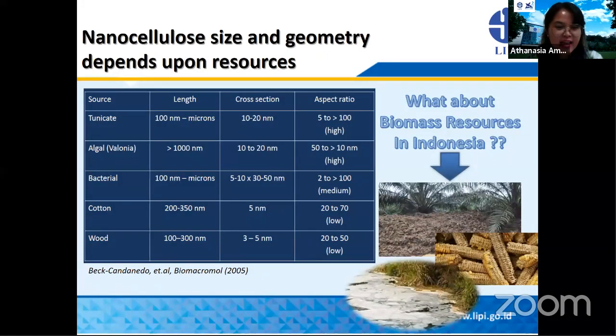Okay, as you can see here, depending upon the resources, the nanocellulose size and geometry will also affect the aspect ratio. For example, I can divide it into two resources. First, non-plant, which is, for example, tunicate, algae, and bacteria. It usually can generate a high aspect ratio. So the aspect ratio is the ratio between the length to the cross-section. Meanwhile, plant resources such as cotton and wood will generate a low aspect ratio, between 20 to 50. So the aspect ratio basically plays a very important role in the properties of the final products.